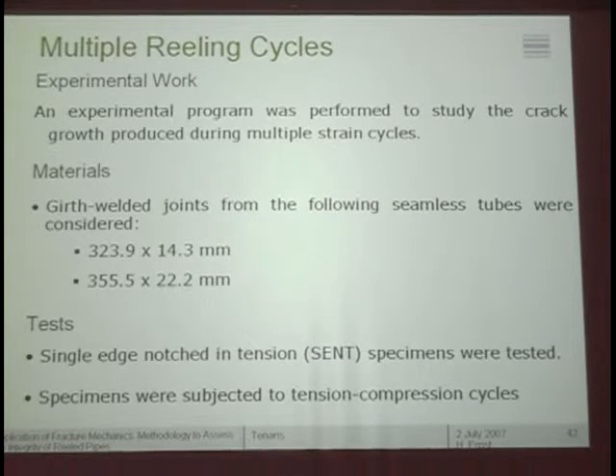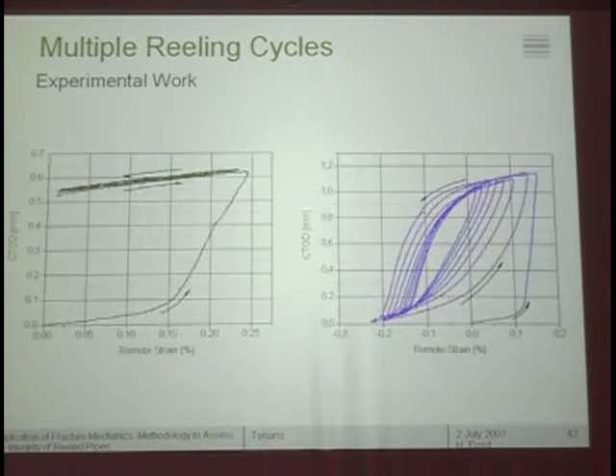We ran again some experimental program to see this part. Material is pretty much the same as before. The test used the same type of specimens as the standard recommends, single edge notch in tension, and the specimens were subjected to tension and compression cycles. I'm going to show you only two examples of the many we ran, showing CTOD measured as before, physically more like a delta 5, versus the remotely applied strain.